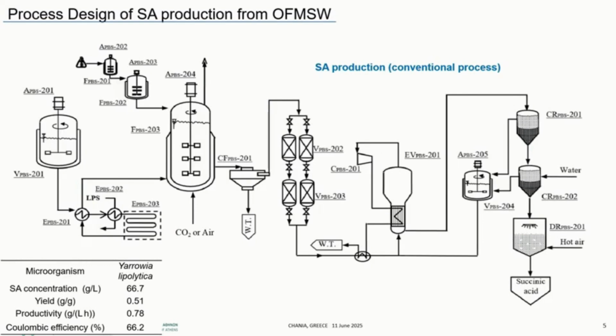also the bioproduction of succinic acid. In this stage, we use sodium hydroxide to control the pH, because succinic acid is an organic acid and reduces the pH to a level at which microorganisms cannot grow. So we use sodium hydroxide in the conventional way to control the pH, and then follows the step of separation of microorganisms using centrifugation, and the remaining liquid, in which the succinic acid is dissolved in the form of a salt with sodium, goes to the resin columns.